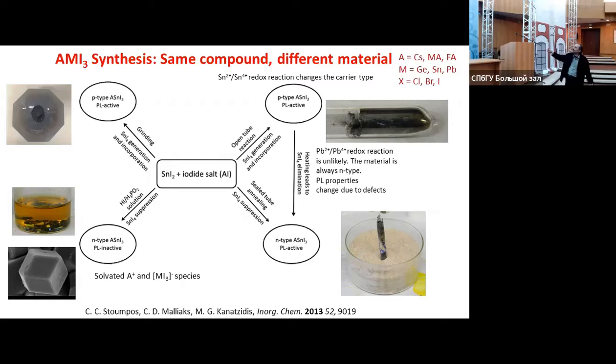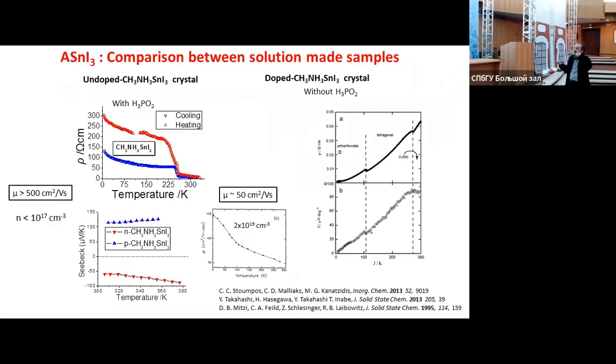So for example, if you melt it, you get a very intense photoluminescence. Typically, if you measure electrical properties, you are on the p-type doped, self-doped region. If you make it from solution, you are on the n-type side, and the photoluminescence is much decreased. And trying to analyze these properties, we try to compare our resistivity data with the data that have been published in the open literature. And we find out that we are approximately 4 orders of magnitude higher in the resistivity compared to the literature or previous attempts, simply because we're using something that prevents self-oxidation of the metal.